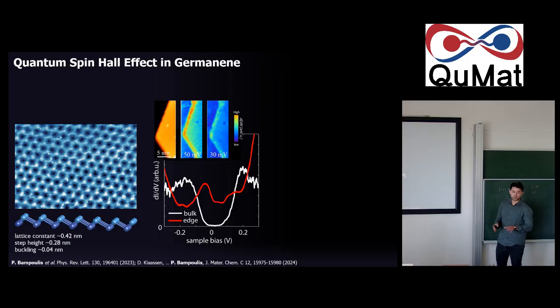And this is an example of scanning tunneling spectroscopy. This is dI/dV as a function of sample bias, a signal that is proportional to the local density of states. If we do measurements on a germanene flake, in the middle of the flake, in this wide spectrum, you see that it has a gap-like feature around 0, whereas the edge itself lights up with these bumps and has quite pronounced metallic states. So we see that the prediction of this edge-bulk correspondence is also experimentally there.